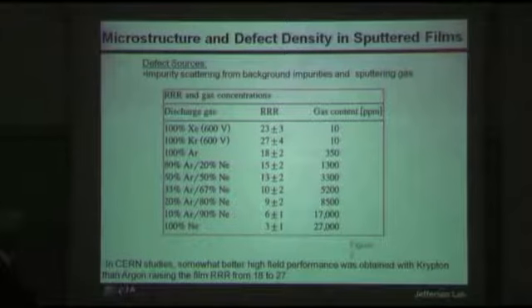And this is a table from one of the CERN papers that is a very nice study showing here for the conventional argon that everyone uses a very high gas content. For krypton, which they have also used and gave some improvement in actual RF results. Here, the improvement in triple R is significant, but not dramatic. And I think that's probably due to the fact that even though there's this reduction in gas content and there are different scattering sources anyway, this is probably dominated by structural defects from the nature of sputtering as a deposition technique.